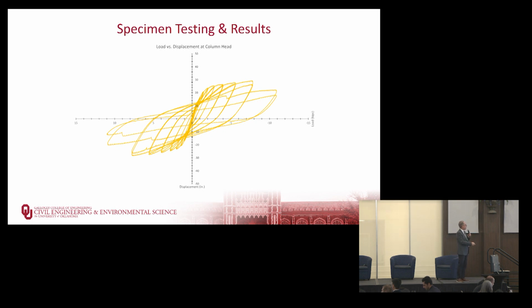So you see an initial linear elastic response, which again, we push very slowly, a very, very small amount in the beginning, but we keep increasing by 40%, so it increases pretty quickly. So you have initial linear elastic response, then the steel. You've got a circular column, so the steel farthest on the outside on the compression and tension faces starts to yield a little bit. The concrete in compression starts to become slightly nonlinear.